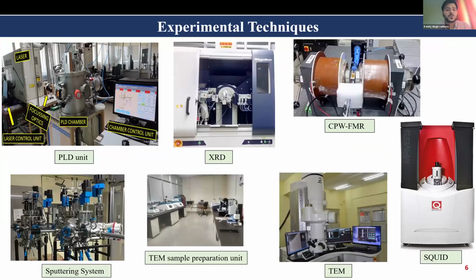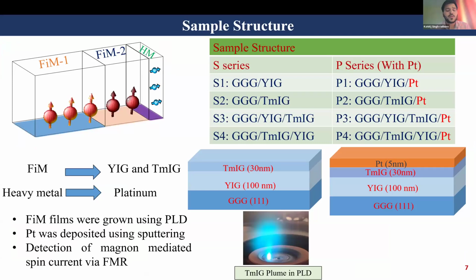For this, we have chosen some of the experimental techniques present at NISER for the deposition of thin films and to structurally characterize them. We have chosen the two ferrimagnets YIG and TMIG and a heavy metal, platinum. We have taken the S series of a single-layer YIG, which is produced using the pulsed laser deposition technique, a single-layer TMIG, and then bilayers of YIG and TMIG, where YIG is on the bottom and TMIG is on top, and vice versa.